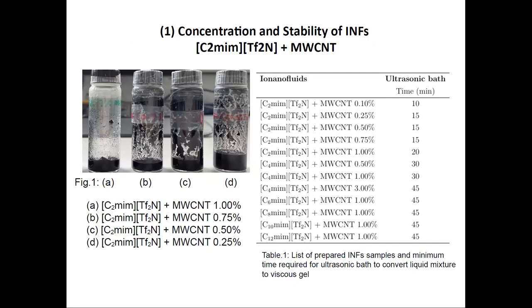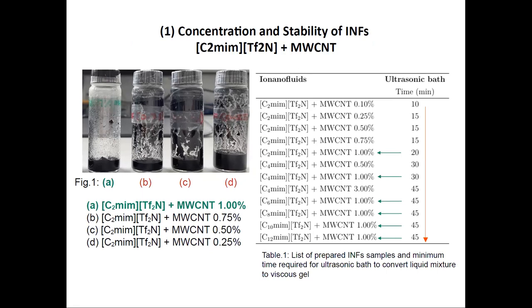The first factor is concentration. In the left figure, four samples with different concentrations in the base ionic liquid are shown. Concentration has an effect on stability — there is a threshold value, after which the samples become stable. I found that 1% is the threshold value. At or above this concentration, after sonication, the ionanofluid sample becomes more stable and remains in the gel-like form. The required ultrasonic bath time increases with the size of the cation — that is, with increasing carbon chain number.